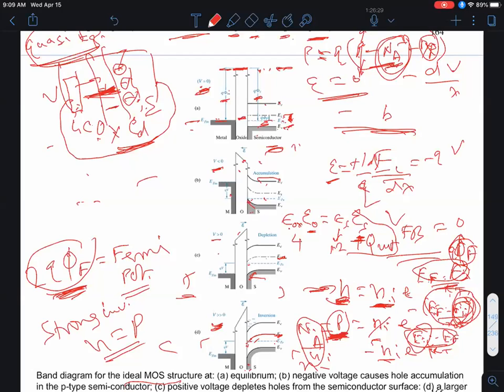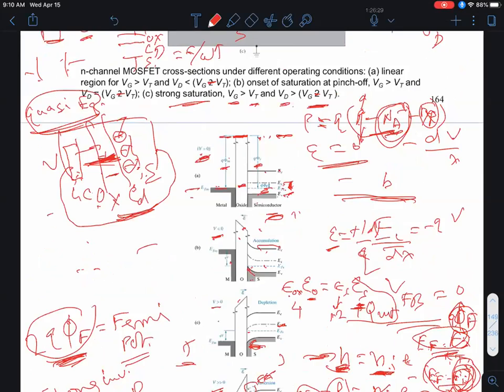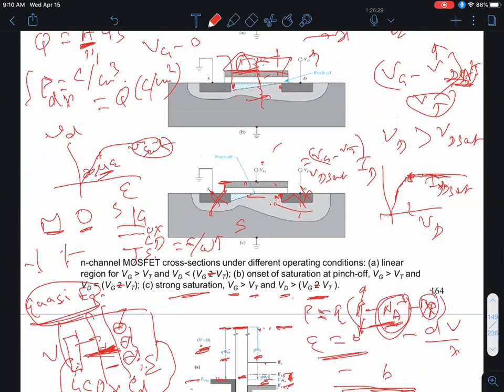If you go beyond the threshold voltage, the approximation is, and it's only an approximation, that the band bending doesn't keep increasing. It gets fixed at phi_f plus phi_f, or 2 phi_f. And all that happens is, as the gate voltage becomes more positive and I dump more and more positive charges on the gate electrode, remember this is an MOS capacitor, you'll have to have corresponding negative charges on the other side. Initially, the negative charges were formed by the negatively charged acceptor ions in the depletion region. But once you reach threshold and beyond, you don't expose any more acceptor ions. The depletion region maxes out at what's called W_max. Instead, you now start dumping more and more inversion charges in the conduction band. And that, of course, is the charge shown in the previous figure.